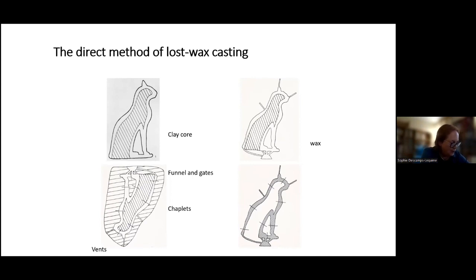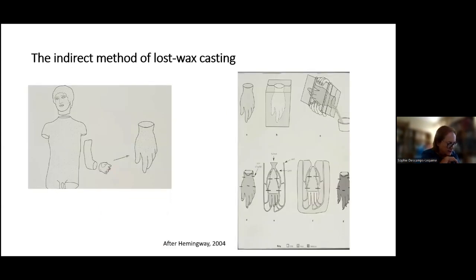After heating the hole to allow the wax to be melted down and evacuated, they then turned it over in order to get the funnel on top, and then poured the molten metal into a funnel connected to gates. After having broken the investment, the figure appeared with chaplets and the network of gates, funnel, and vents. The chaplets were removed, the channels cut. But the innovative process was that of indirect lost wax hollow casting,